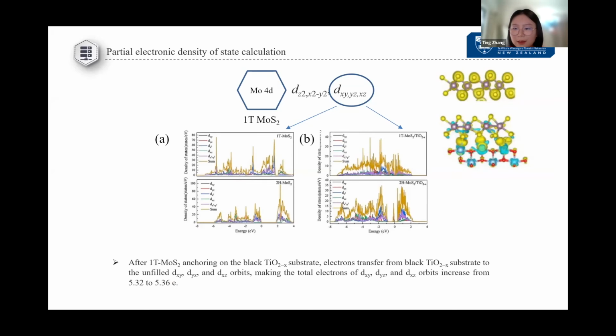And we can see the electron does transfer from the interface between titanium dioxide and MoS2. So we make the conclusion that after the decoration of 1T-MoS2 on titanium dioxide, the electrons of dxy, dyz, dxz are enhanced, and that's why the 1T-MoS2 can have enhanced stability during the reaction.